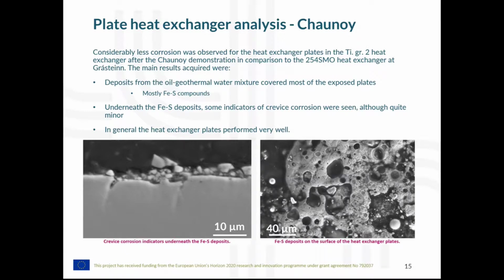And underneath these iron sulfur compounds or deposits, we saw some indicators of possible crevice corrosion, as you can see on the bottom left picture, although these indicators were quite minor. So in general, the heat exchanger plates performed very well at Chaunoy.